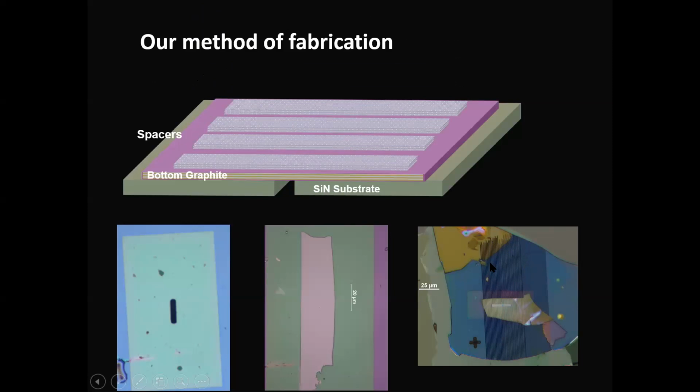You can etch in between the graphene, and then you can make graphene lines. You can transfer these lines using the polymer that we have. We know how to make heterostructures. We have learned from heterostructure fabrication that we can transfer one flake to another. So we used the same technique, and we transferred these lines on top of the graphite.